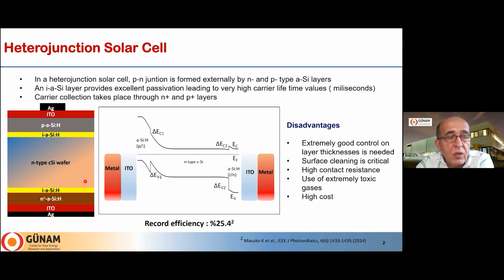Okay. So this is the structure that generates very high efficiency. Actually, the record efficiency is about 25% at the moment. Here you see the band diagram. Here, of course, the region between metal and the substrate, we have an ITO layer. This is indium tin oxide, or some other alternatives can be used here, like zinc oxide, etc. So this layer should be transparent to the light, but it should be very highly conductive to collect the current. So we have high efficiency, very good passivation, and very promising technology.